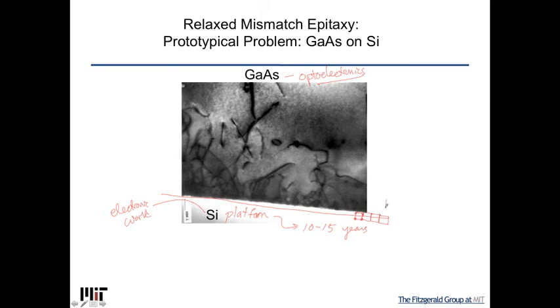And it turns out gallium arsenide has a bigger box. So when its atoms are fully relaxed at their native spacing, and I want to put this one on this one, there's clearly a problem because the atoms don't line up. And that's a problem because when the atoms come down, they're coming from a vapor phase. They're all flying down, and they find their spots on the crystal of silicon. So naturally, when they first form, this layer is going to be squished. If you will, it's going to look like this, right?